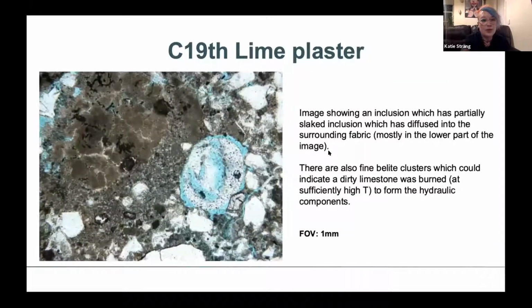But then when you look at closer details at these lime inclusions, you start to get an idea of what's going on. So again, in this one here, it's diffused quite well into the surrounding binder. You can't see much of an interface between those two. So that means that that inclusion itself would have been acting as binder, not as aggregate, which is important when you're thinking about your mix proportions.